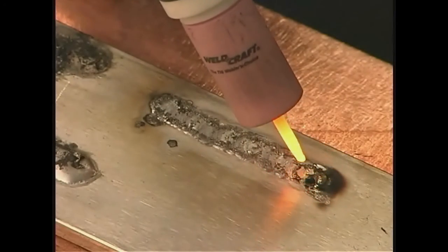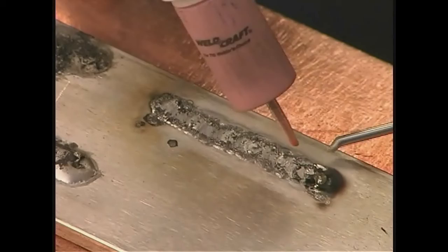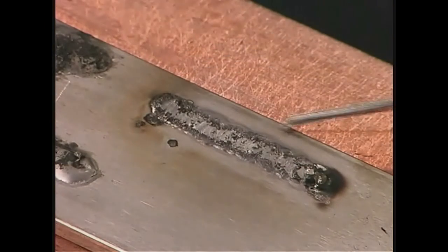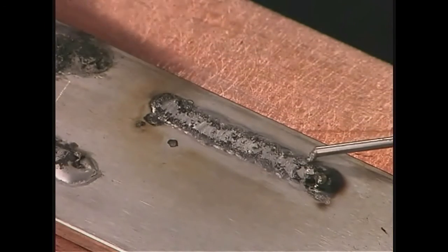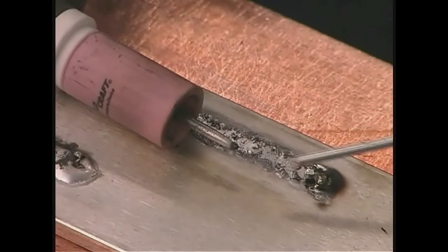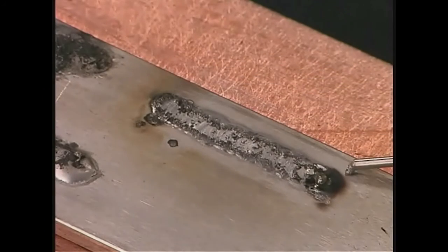So even though I had a full 18 cubic feet per hour of argon flowing, because the tungsten was extended so far, I didn't have proper shielding on this weld, and you can see this weld looks just as lousy as the previous three. So this shows the importance of having enough shielding gas in the weld area.